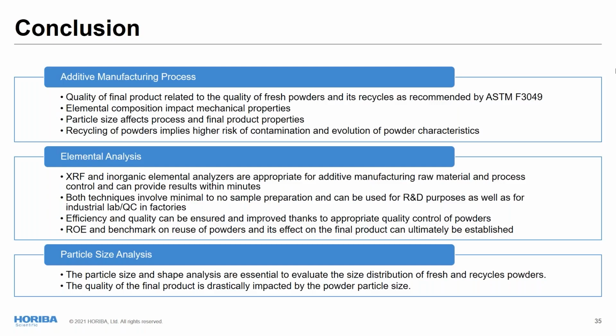And also remember when we were talking about the powder bed on the printing, there are specifications, right? If you're using laser, if you're using electron beam. So for the lasers from 20 to 40, and for electron beam from 50 to 70 micrometers. So if your particles grow too much and surpass this threshold, I'm sorry, it's time to recycle. Of course we don't want to lose that, but it's time for you to recycle.